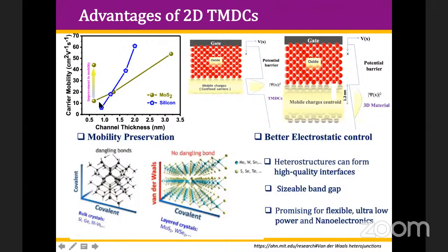Mobility is significant, clear. Secondly, dangling bonds. In the case of 2D material, there is no dangling bond because layer by layer interaction is by van der Waals interactions, whereas in 3D material, their interaction layer by layer is covalent bond. In the Z direction also a covalent bond is there. So if you are going to make a slice of small thickness, it will lead to dangling bonds in the conventional semiconductor.